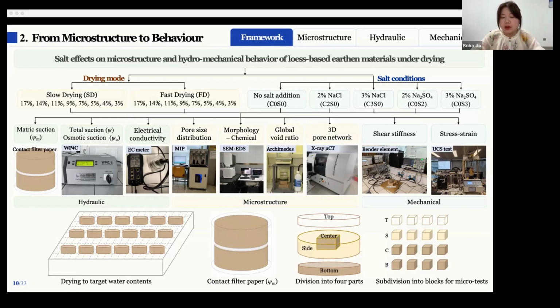At equilibrium, the soil and the filter paper share the same suction. Using a well-established relationship, the matric suction of the soil can then be determined. And the parallel samples were cut into 4 parts: top, bottom, sides, and center, and each part was further divided into small blocks of about 3 millimeters for subsequent tests, including total suction measurements using a hygrometer based on the Kelvin equation, and the electrical conductivity to represent the salt distribution, and the mercury intrusion porosimetry, MIP, for pore distribution, and the scanning and SEM for the morphology and